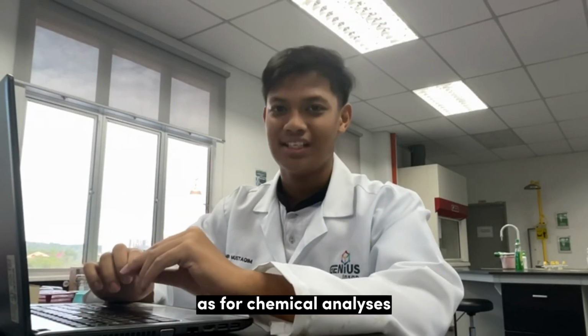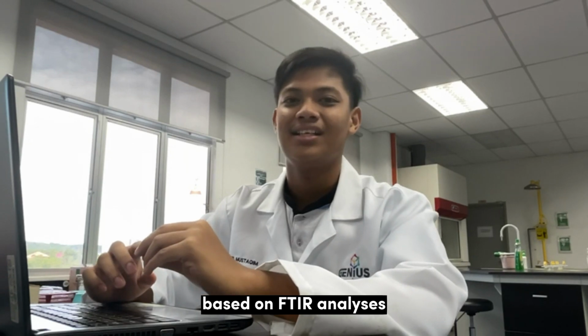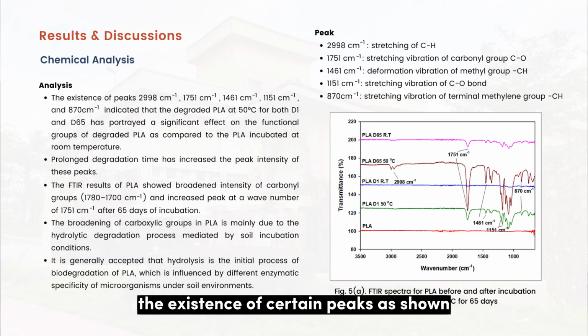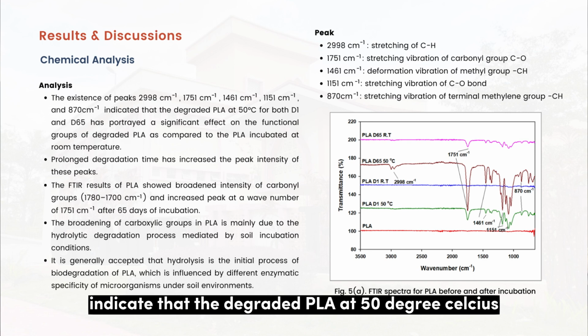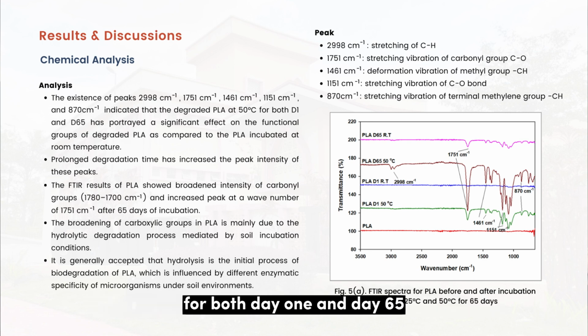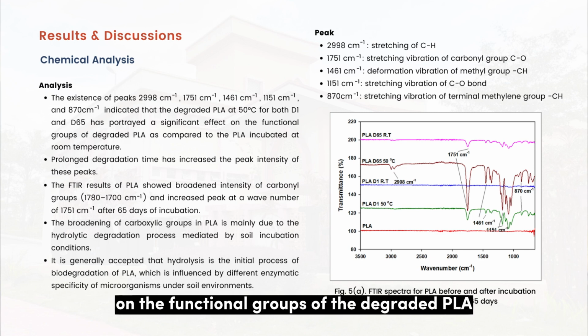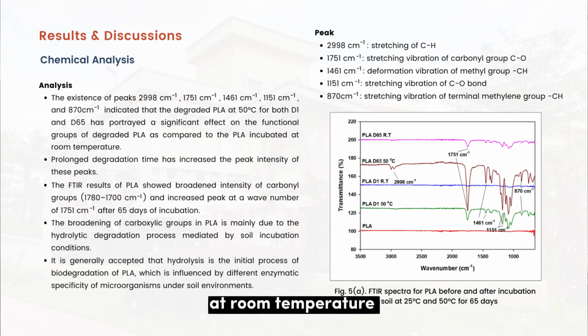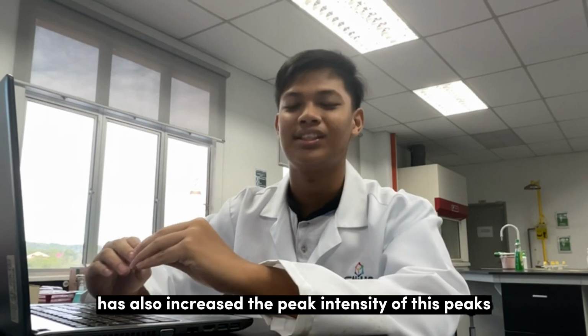As for chemical analysis, based on FTIR analysis, the existence of certain peaks as shown indicates that the degraded PLA at 50 degrees Celsius for both day 1 and day 65 has portrayed a significant effect on the functional groups of the degraded PLA as compared to the PLA incubated at room temperature. Prolonged degradation time has also increased the peak intensity of these peaks.